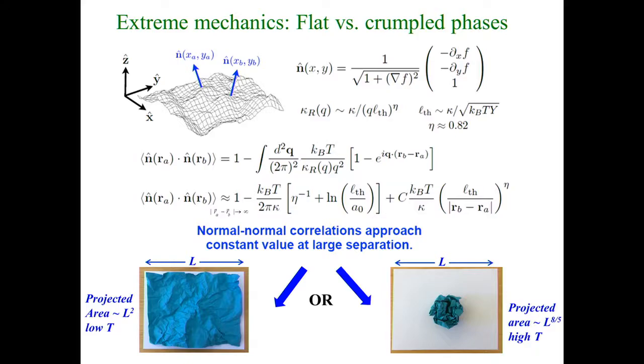And so here's a cartoon of that object, and its projected area related to the fractal dimension of this object, which I hope some of you mathematicians will explain and understand. I would love to know its fractal dimension from some first principles analysis. Its projected area doesn't go like L squared, it goes like L to the 8/5, corresponding to a fractal dimension that's neither 2 nor 3-dimensional, maybe more like 2.5, 2.4. So, okay, great. So we go out, we find our experimental friends, and perhaps over a beer, soften them up. Say, oh, raise the temperature, look for the crumpling transition of graphene.